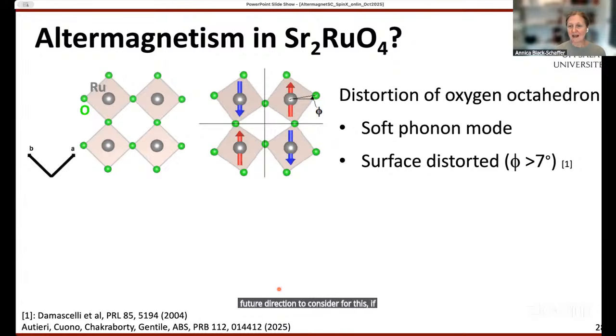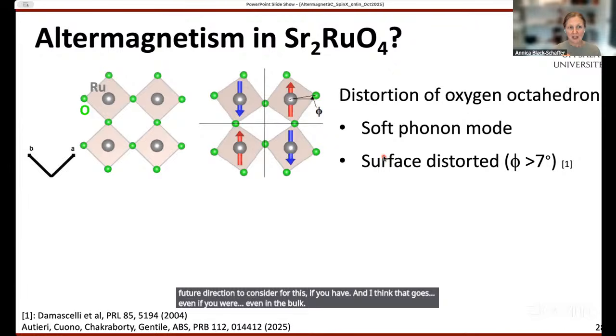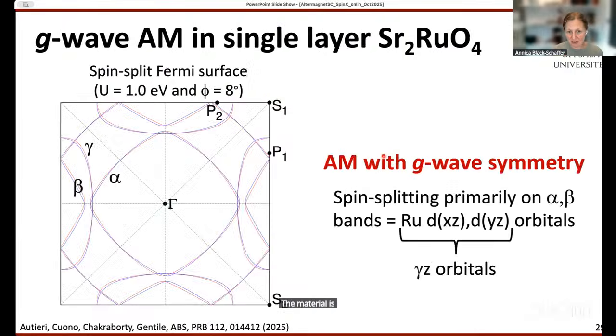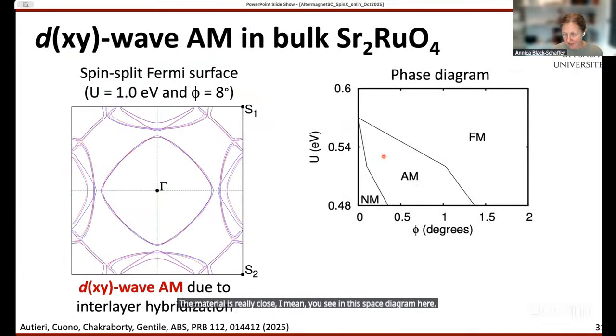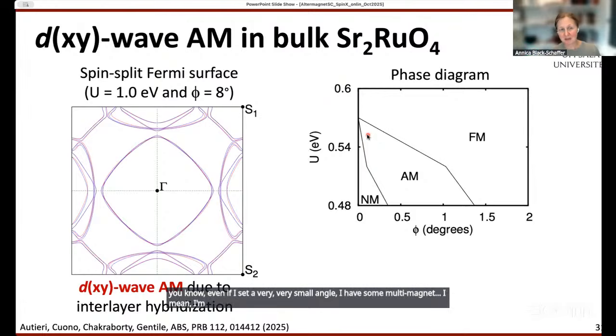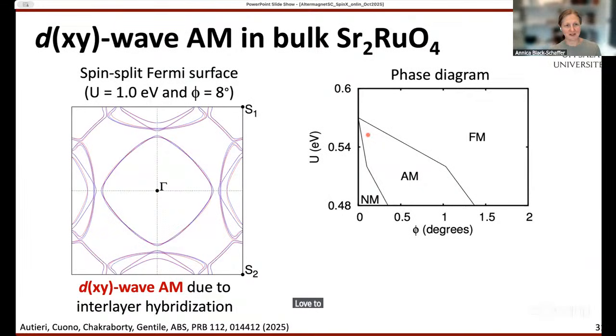And I think that goes even in the bulk, where you don't have this distortion, the material is rather close. You see in this phase diagram here, even if I set a very, very small angle, I have some altermagnet. I'm closer to the altermagnet in some sense than the ferromagnet. I don't know if the fluctuation having an altermagnet property makes a difference to the superconducting state I can get. That's a big open question that I would love to answer, but I don't have an answer to.